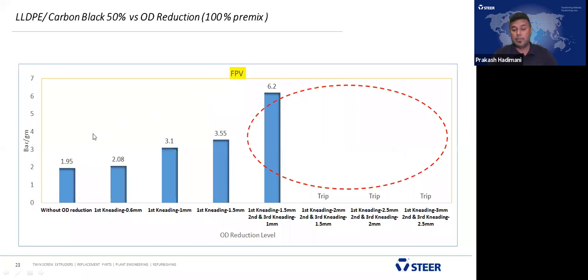In the case of carbon black, it's 50% carbon black. The filter value without OD reduction, approximately 2 bar per gram. And slowly, it is gradually increasing, the dispersion quality poorer at 3.5. And in the case of first kneading 1.5 millimeter, if you say 0.75 both the side, second and third section, we're getting 6.2 bar per gram. It's very poor quality of dispersion.